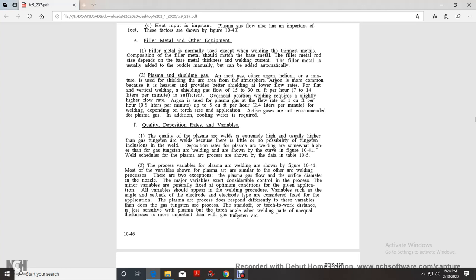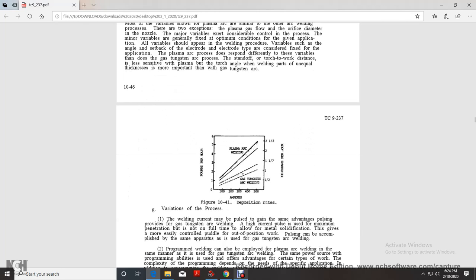All variables should be considered. Variables such as the angle, the setback of the electrode, and electrode type are considered fixed for the application of the plasma arc process. It does respond differently to these variables than the gas tungsten arc process. The standoff of the torch to work distance is less sensitive with plasma, but the torch angle with unequal part thickness is more important than in gas tungsten arc welding.